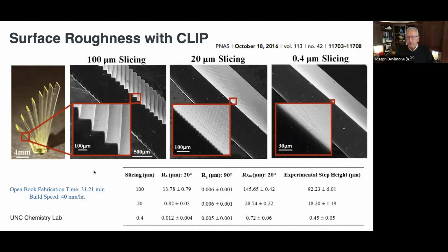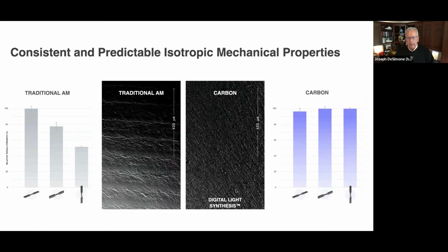Gets to really smooth surfaces when you do it this way. And it also leads to isotropic parts. Because if you slice open a traditionally polymerized or made part, you'll see the individual layers leading to anisotropy depending on the orientation of how you print them. When you run these free radical 100% UV curable systems this way, you can get to isotropic parts.